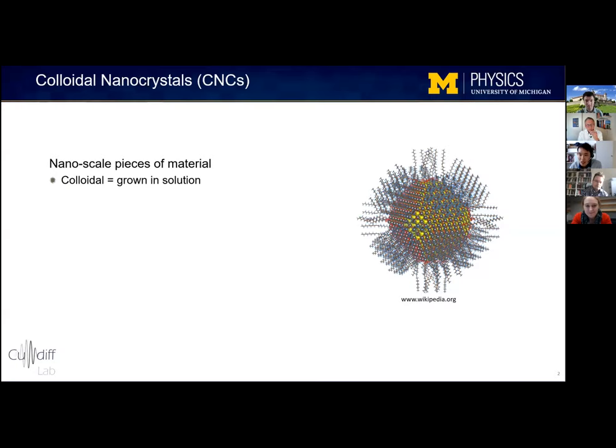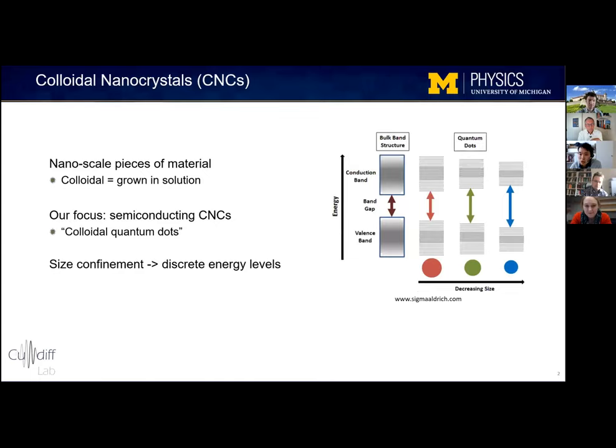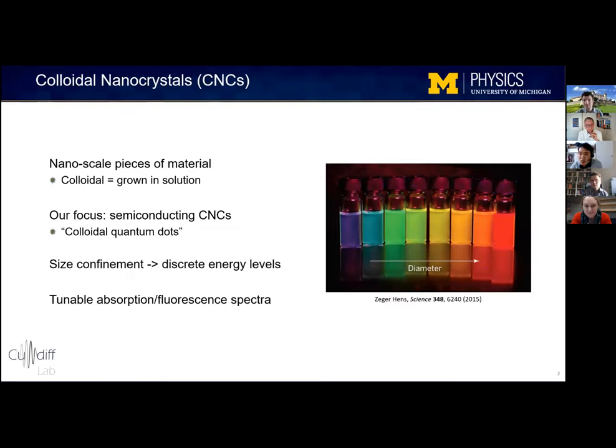So what are colloidal nanocrystals? Colloidal nanocrystals are pieces of material whose dimensions are on the nanometer length scale, and they're colloidal, which in this context means that they're grown in solution. And specifically, we study colloidal nanocrystals made of semiconductor, which are often called colloidal quantum dots. And in colloidal quantum dots, the quantum confinement, due to their small size, gives rise to discrete energy levels. So by changing the nanocrystal size, you can change the energy gap of the material.